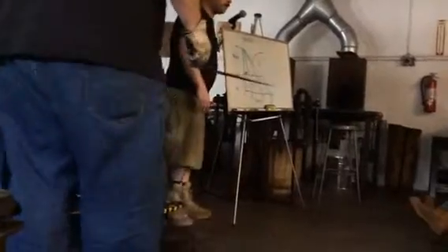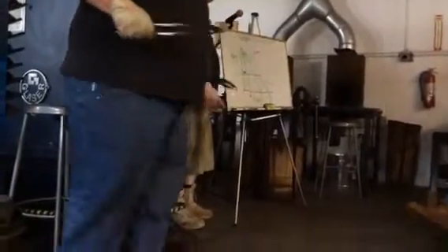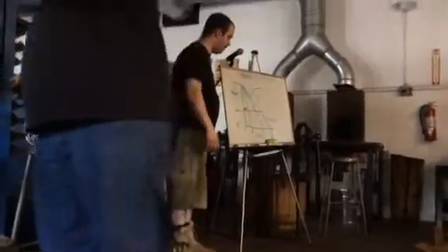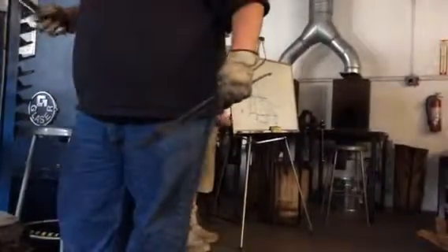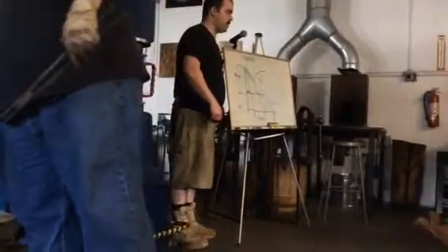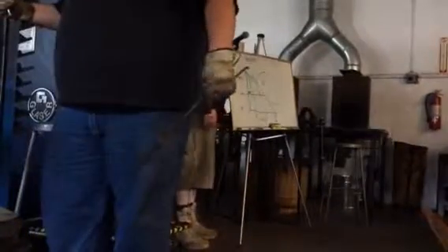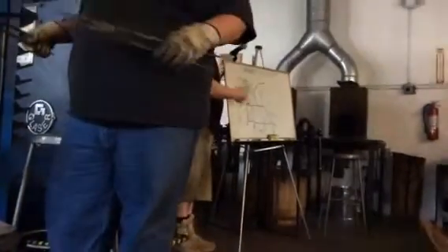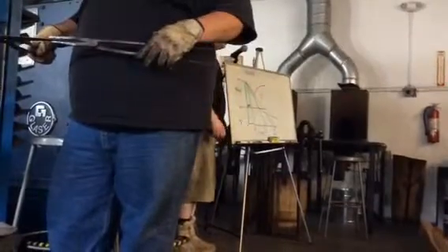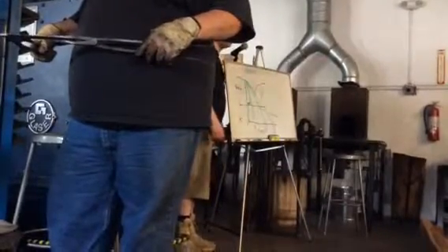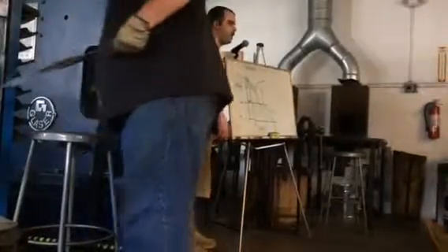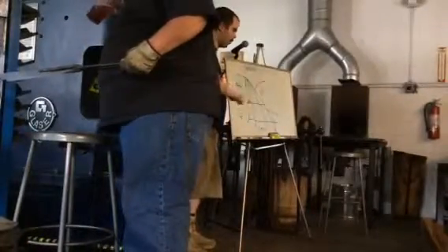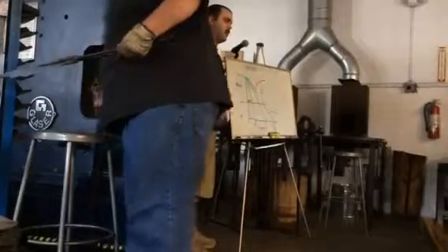So is that the normalizing step that you did? Yeah, that's a normalization. Okay. If you feel that your grain structure is really, really jacked up, you can throw a quench in that cycle to really refine the grain. Like really dragging it, kicking and screaming, and making it hard steel to refine the grain. If you're starting out with large grains, you're still going to end up with large grains. So it's not really something you can just quench.